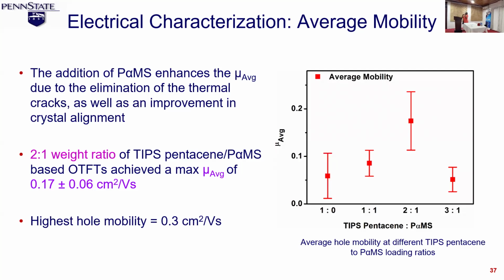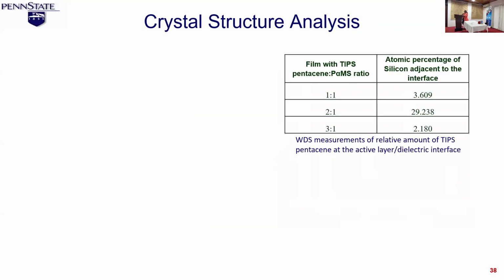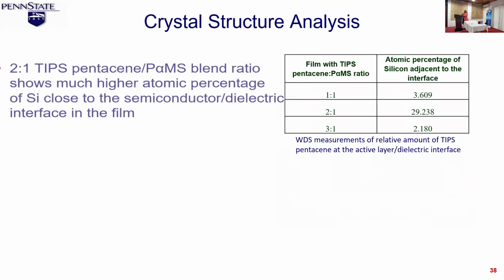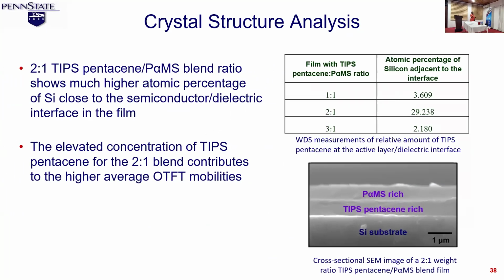So then I was wondering why, again, from the morphology, they all look the same, but why do we have such a high jump in the conductivity? And what I did was some type of characterization where I actually looked at the cross-section of the film. So what happens actually when you blend the materials and they crystallize is that they separate. It's called vertical segregation or vertical phase separation.